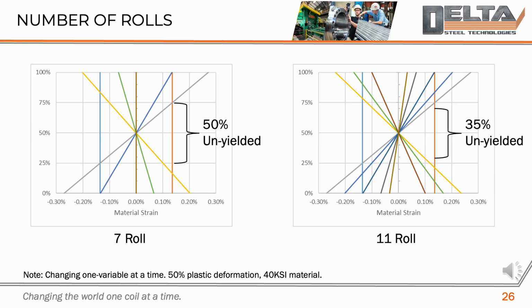With fewer rolls, the material experiences fewer bending cycles, meaning the penetration and strain at each bend are more concentrated. As a result, a larger unyielded area remains, indicating that more of the material stays within the elastic zone. While 50% plastic deformation is achieved, the fewer bending cycles limit how much of the cross-section is permanently altered. The 11-roll leveler. In contrast, this configuration introduces more bending cycles, distributing the deformation more evenly across the material. This reduces the unyielded area compared to the 7-roll leveler.